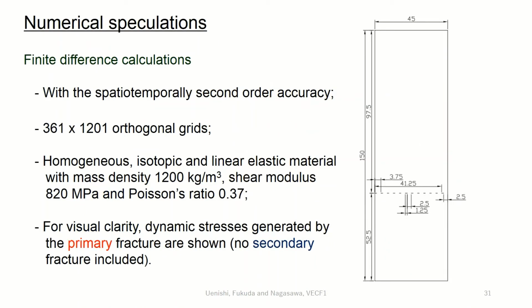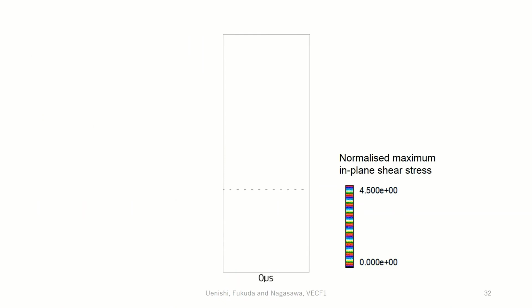Let us move to the numerical part of the study. Finite difference calculations have been performed with the spatio-temporally second-order accuracy, with 361 times 1201 orthogonal grids, for a homogeneous, isotropic, and linear elastic material with mass density 1200 kg per cubic meter, shear modulus 820 MPa and Poisson's ratio 0.37. For visual clarity, here, dynamic stresses generated by the primary fracture are shown, with no secondary fracture included. As in the experimental photographs, contours of the maximum in-plane shear stress will be depicted.